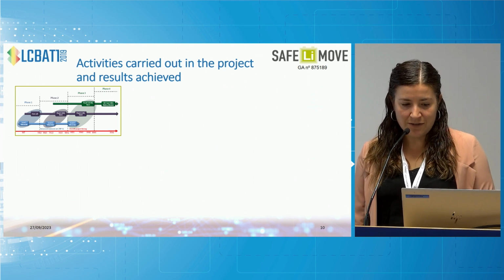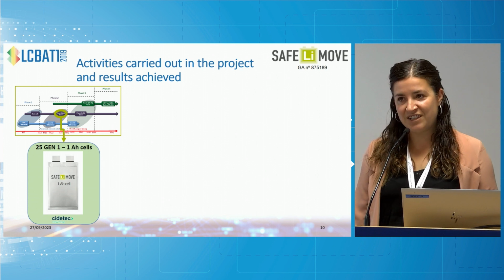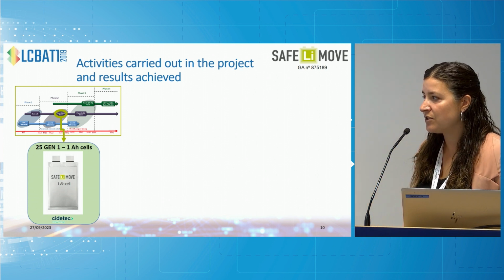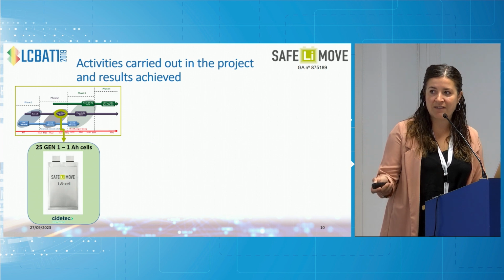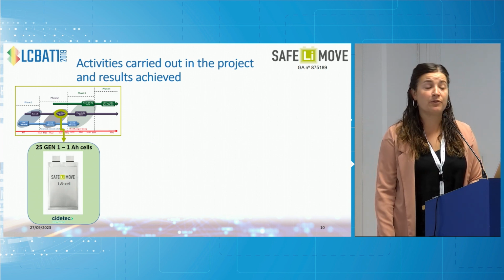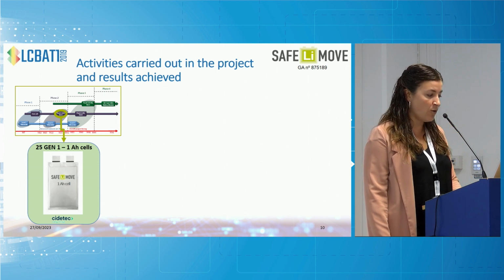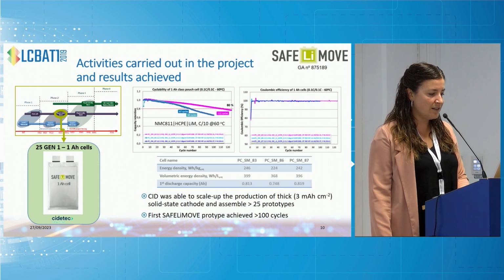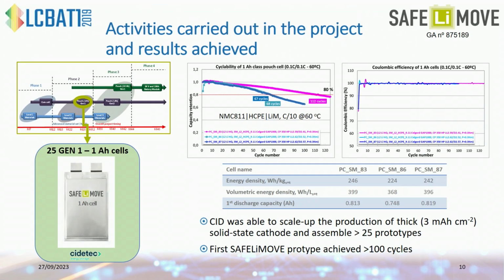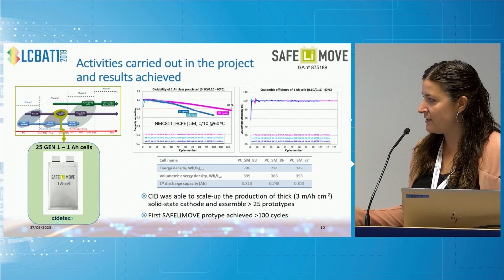So all these materials together led us to the first generation of 1 ampere-hour cells. As I was saying before, this was a scale-up by CIDETEC, and they were able to manufacture more than 25 cells in order to be shared with all the partners involved in the testing. And what we found with this first generation of SAFELIMOVE solid-state cells were that we were able to have a pretty good result on cycling at 60 degrees, up to beyond 100 cycles, with a really good coulombic efficiency in all the cases. And if we translate this into energy density values, here we are summarizing in this table.